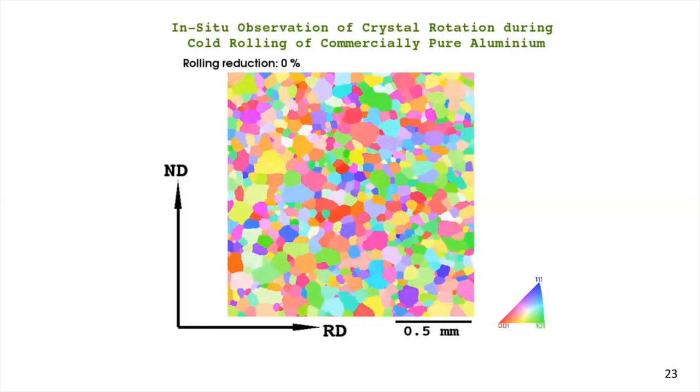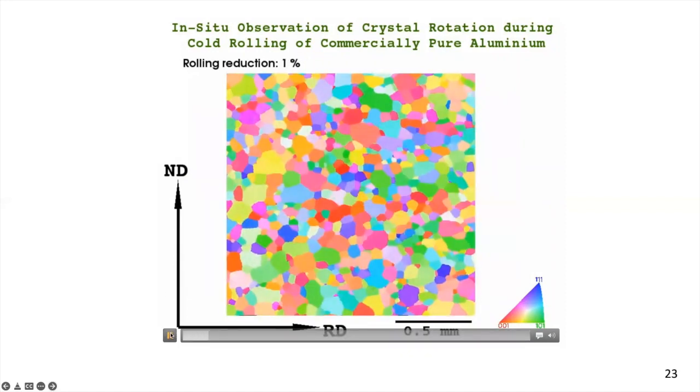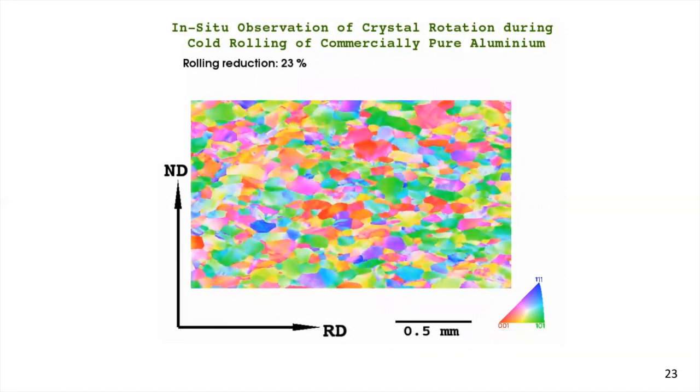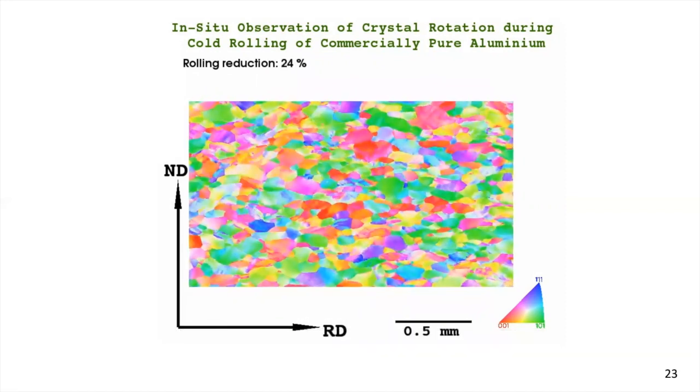So this is not an animation. This is the real evolution of the microstructure, and you can see how the material plastically deformed and how the crystals rotate, as predicted by crystal plasticity models.